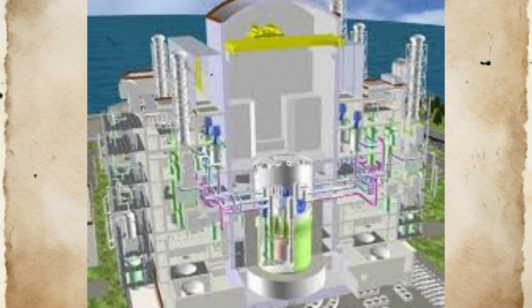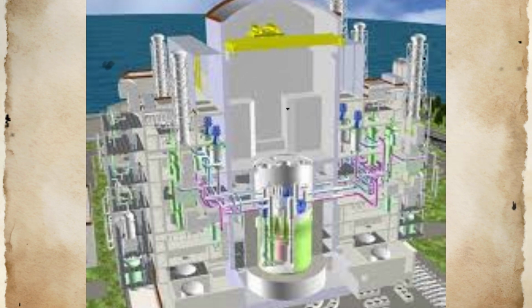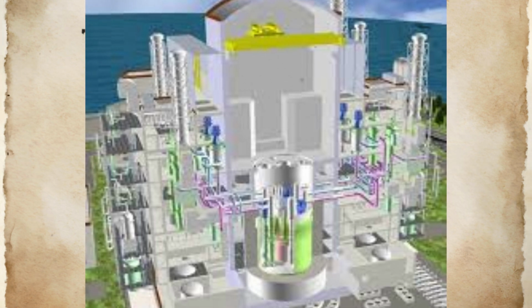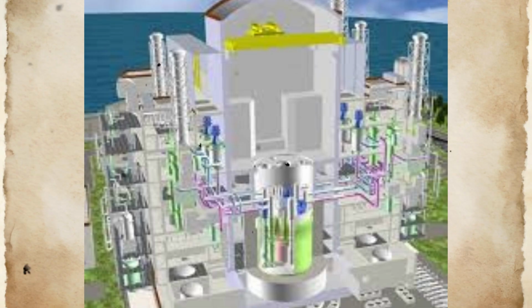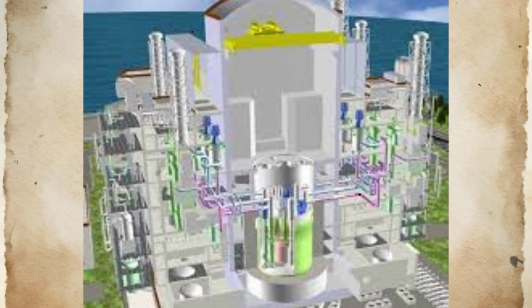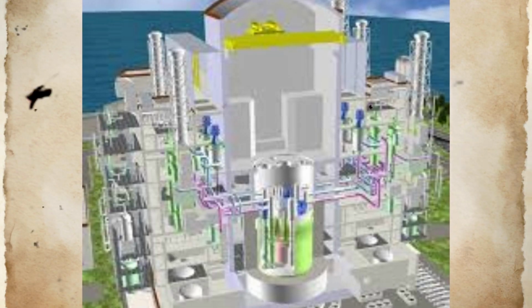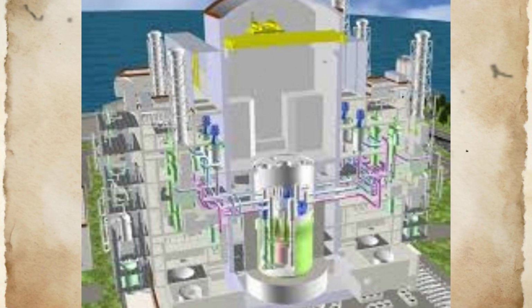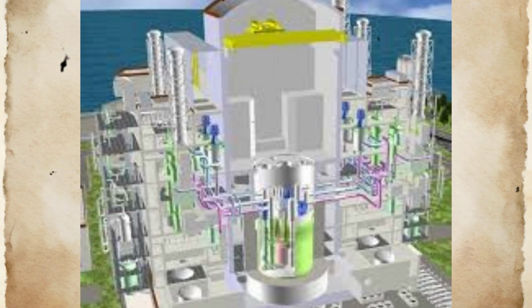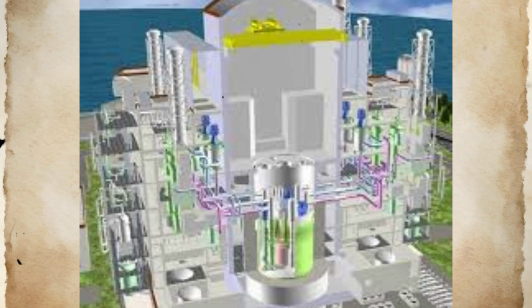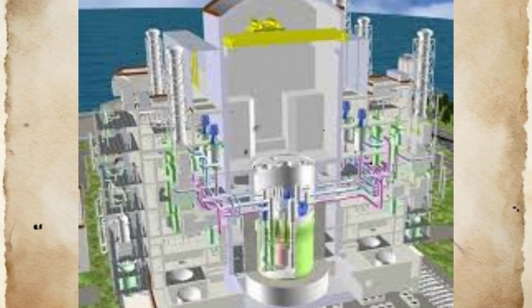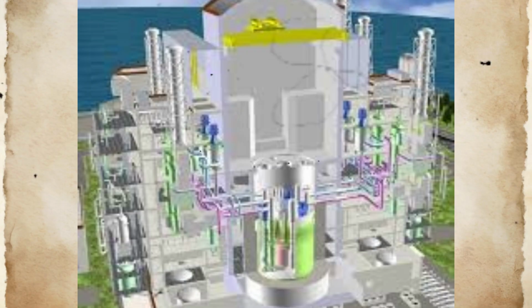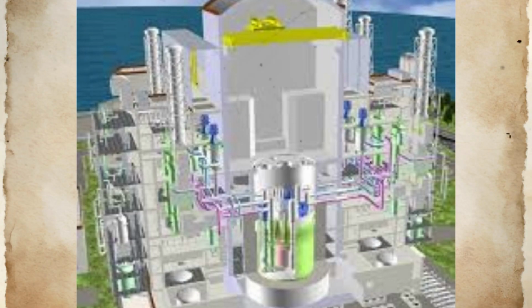The fracture of the thermocouple well tip created a direct communication path between the pressurized secondary heat transport system and the atmospheric environment of the piping room. At the moment of final separation, sodium at approximately 505 degrees Celsius and elevated pressure began flowing through the newly created opening, at a rate determined by the pressure differential and the effective flow area of the fracture geometry.